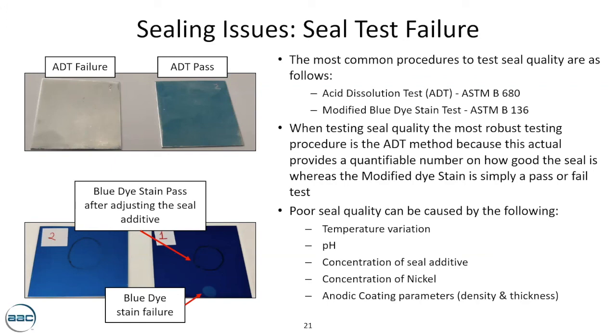The part on the left was sealed in a seal where it did not have the correct amount of additive in it, and the part on the right went through the test after the content of the additive was modified. When testing seal quality, the most robust testing procedure, as I told you, is ADT, because it actually gives us the quantifiable number on how good or bad a particular seal is, whereas the modified dye stain test only tells us a pass or a fail of the test.